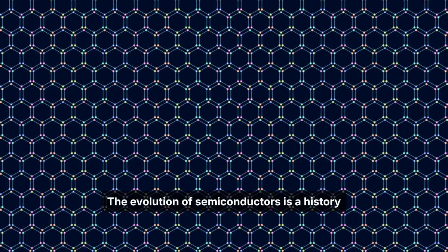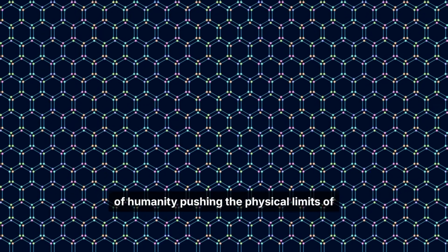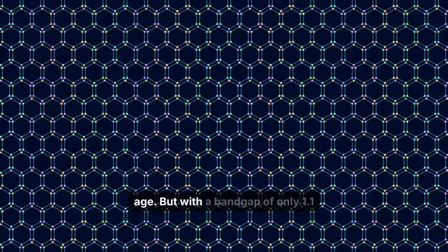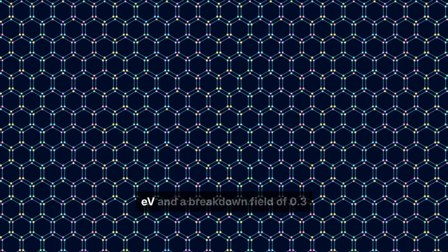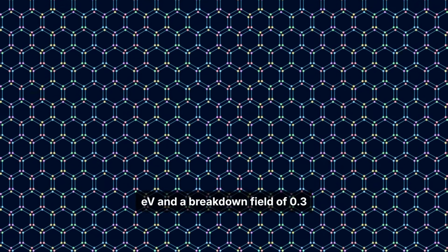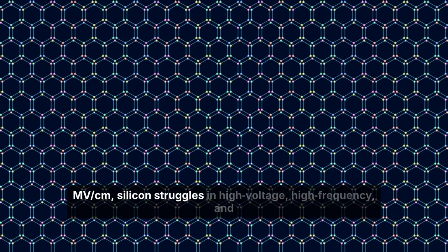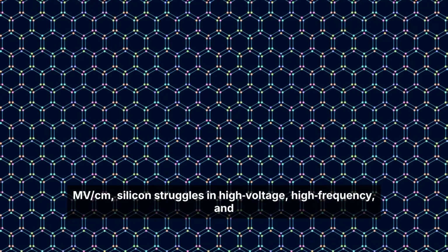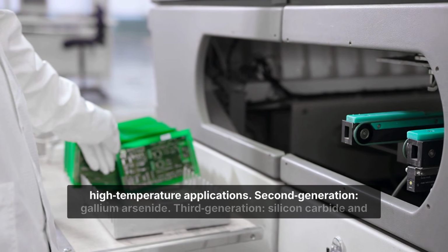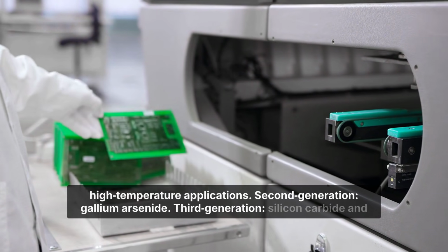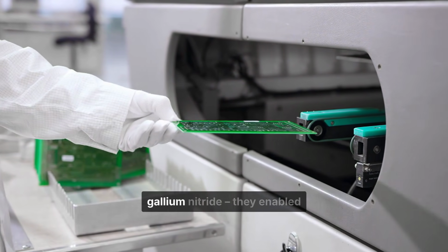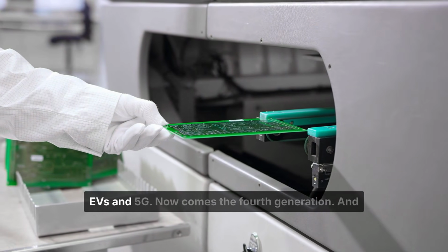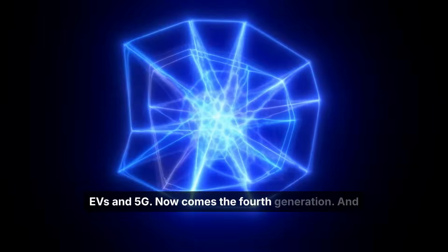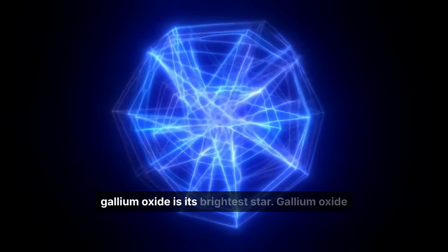gallium oxide. The evolution of semiconductors is a history of humanity pushing the physical limits of materials. First generation silicon built the information age, but with a band gap of only 1.1 eV and a breakdown field of 0.3 MV/cm, silicon struggles in high voltage, high frequency, and high temperature applications. Second generation gallium arsenide, third generation silicon carbide and gallium nitride. They enabled EVs and 5G. Now comes the fourth generation, and gallium oxide is its brightest star.